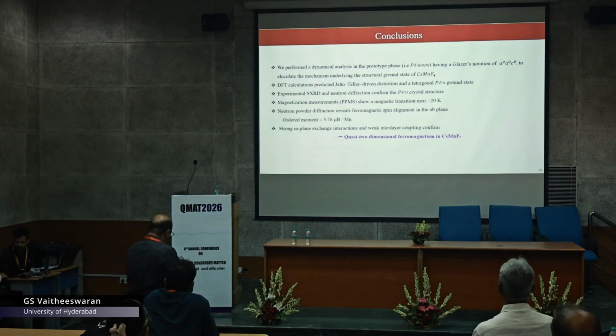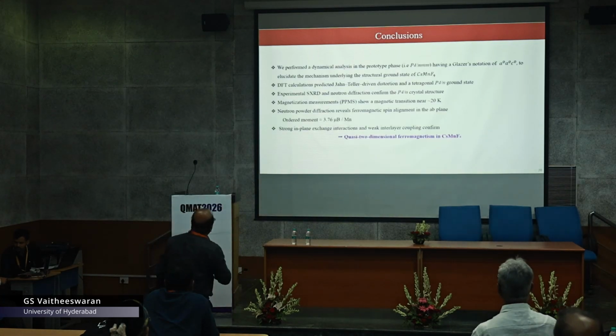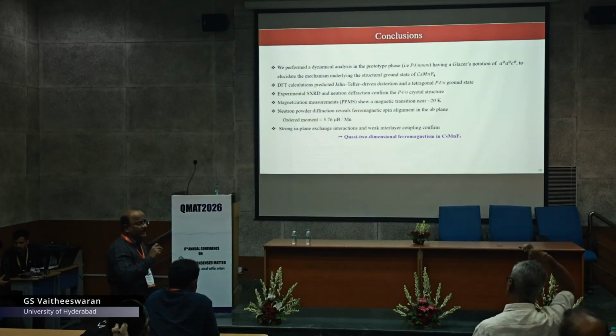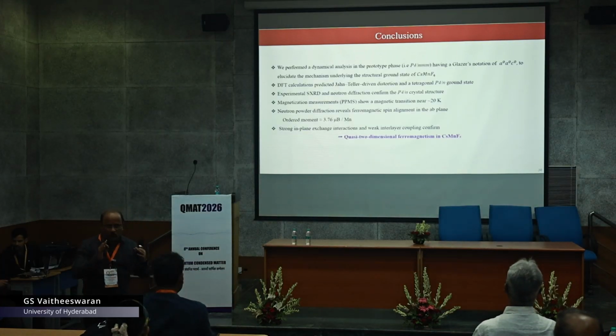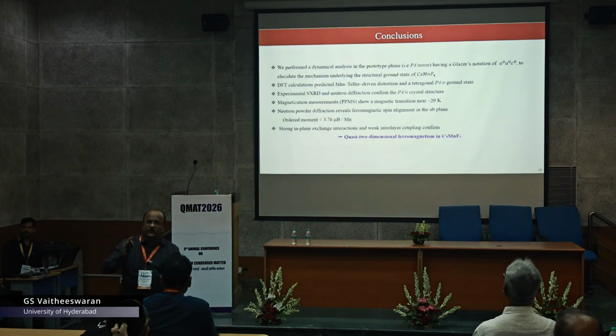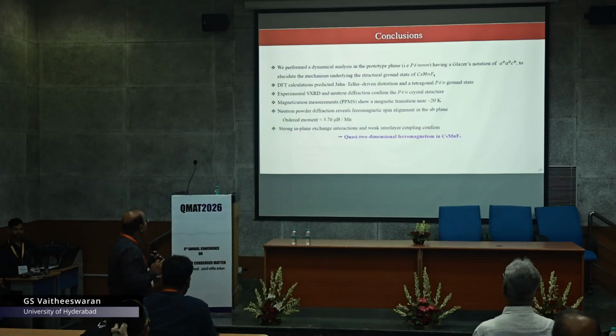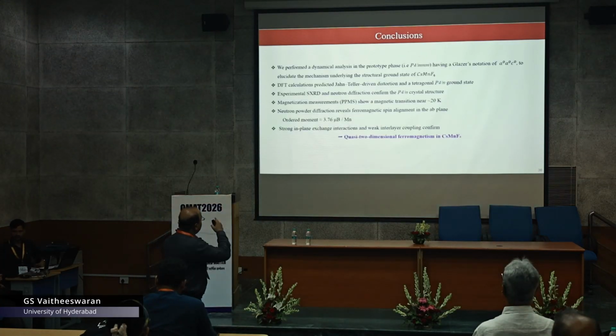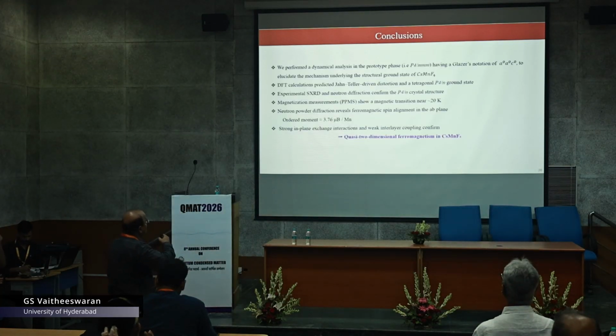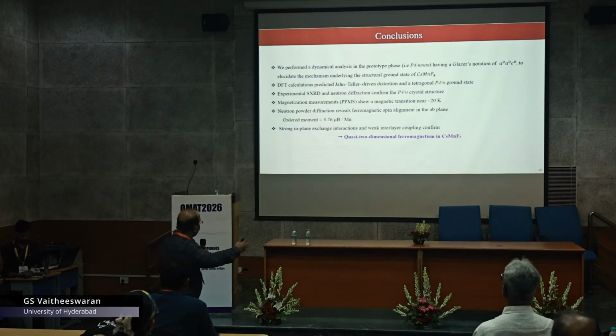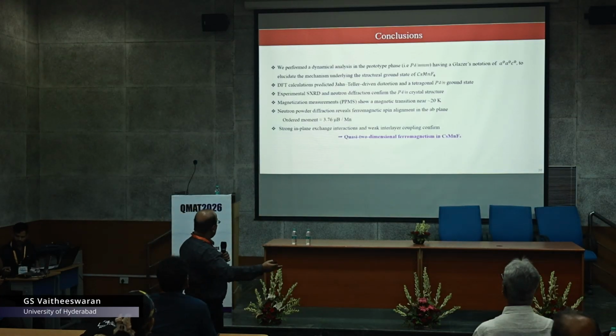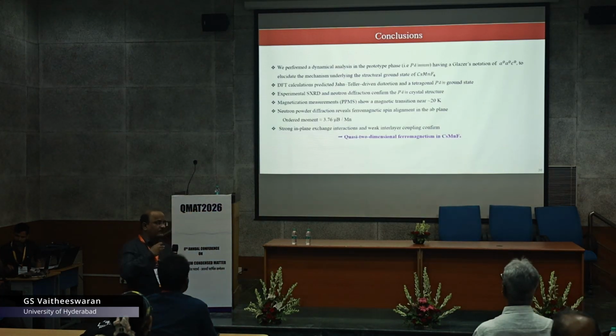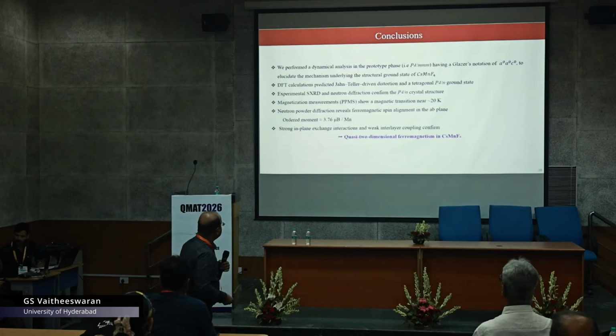Yeah, so I would like to conclude that. We performed these unbiased calculations through phonons, and then tried to confirm the ground state of this particular system. We say that, instead of P4 bar NMM, the system prefers this P4 bar N space group, which is also tetragonal, which was first predicted by theory and confirmed by experiment.